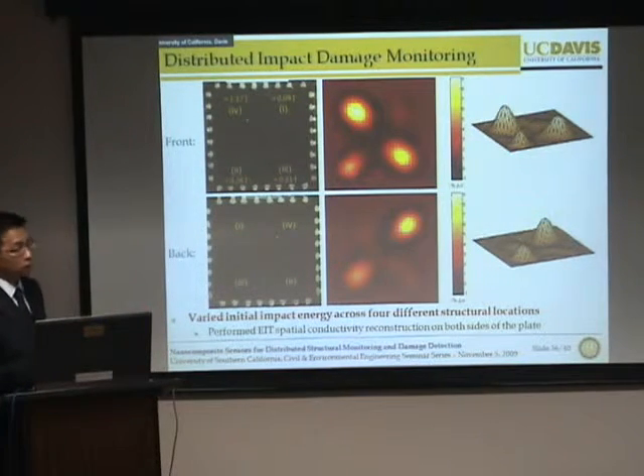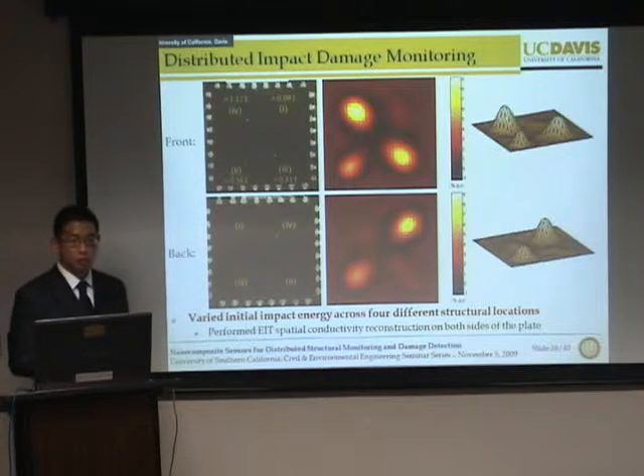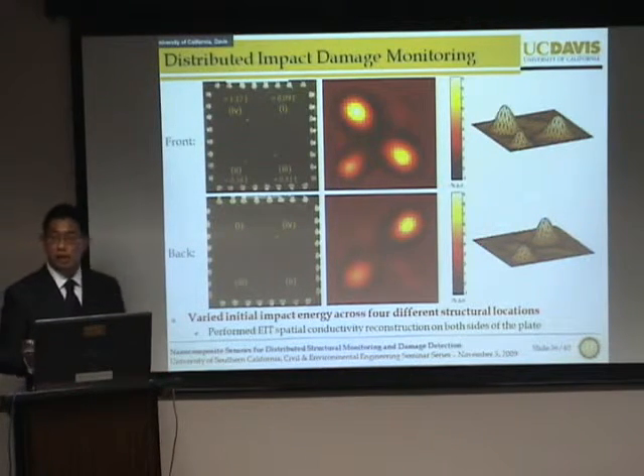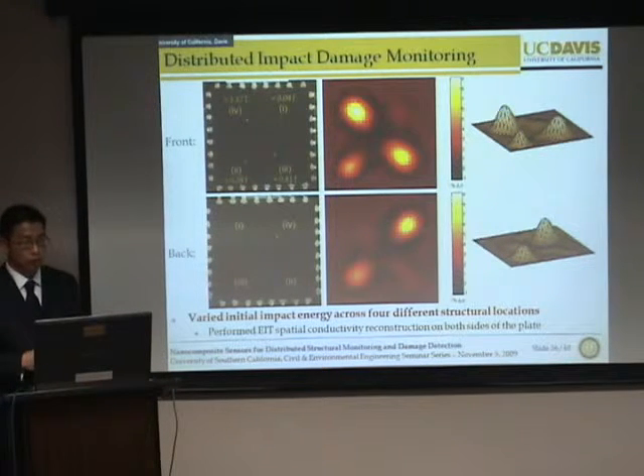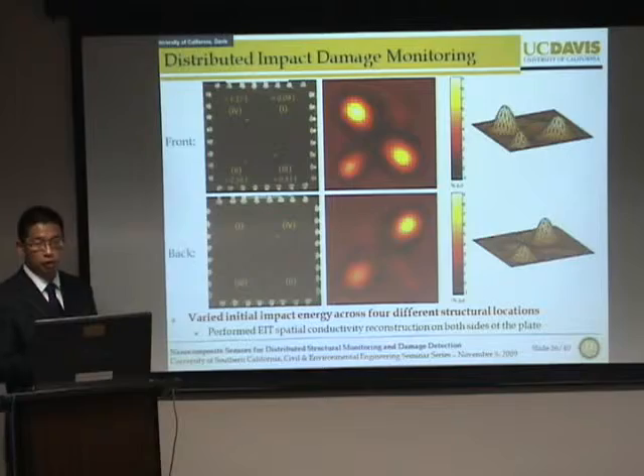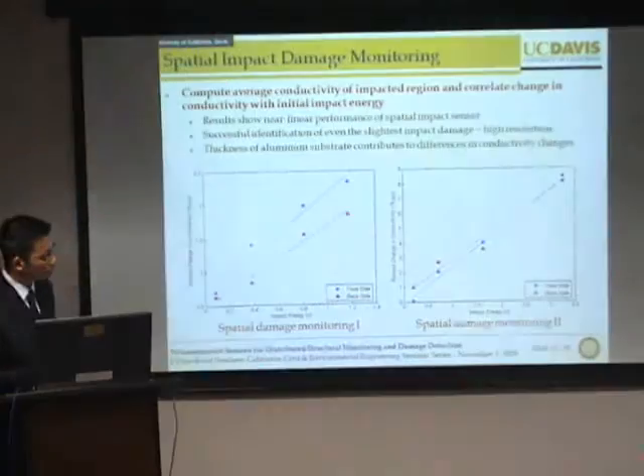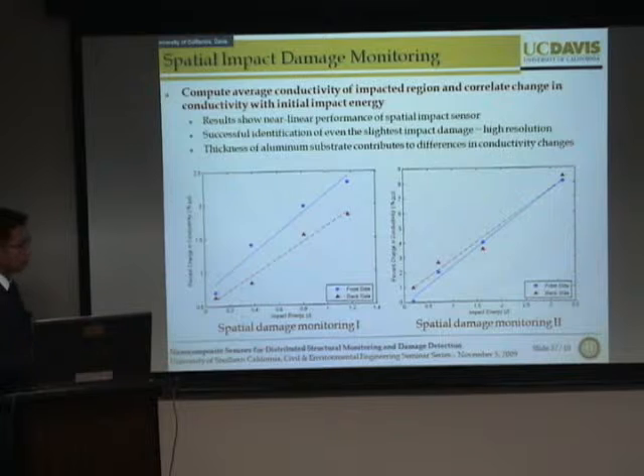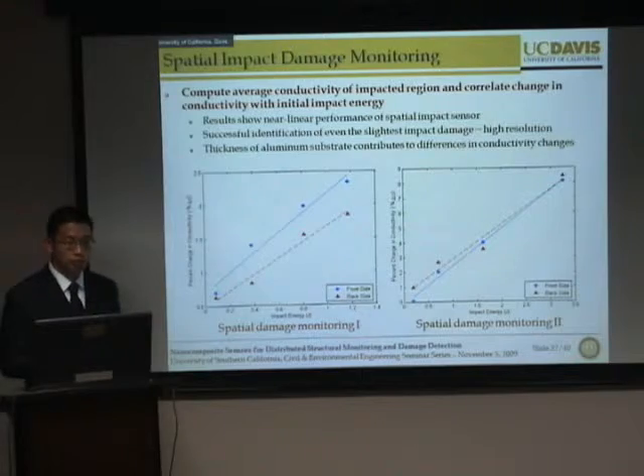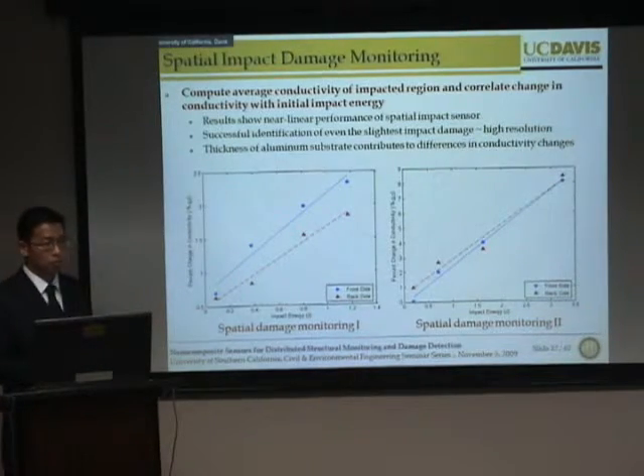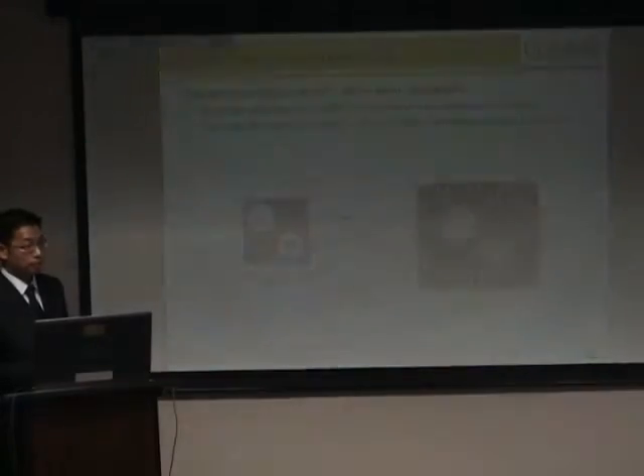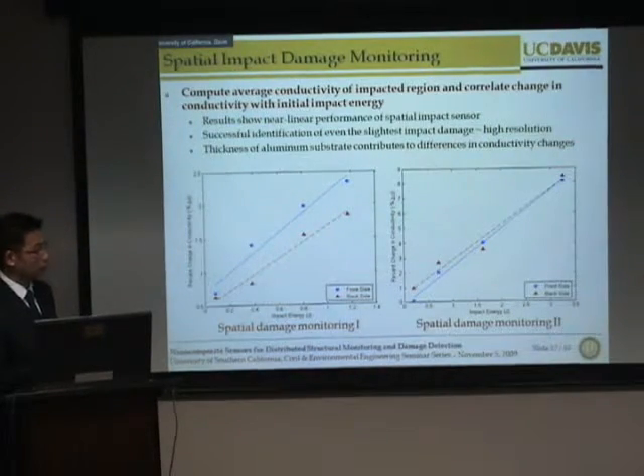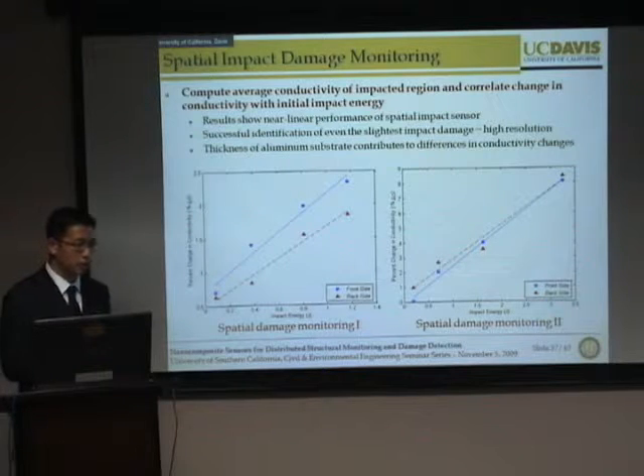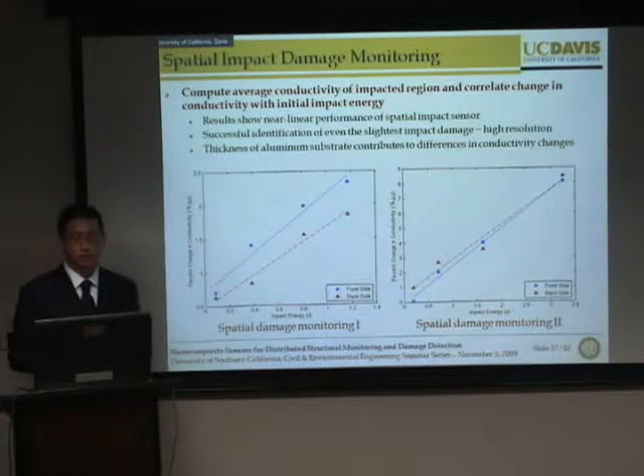So now with this technique, not only are we able to identify the magnitude of damage based on change in conductivity, we're also able to isolate where the location of damage has occurred. And you can see that we could plot it in 3D for easy visualization of damage. And we can do some data analysis to look at how the percent change in conductivity varies with impact energy. And we see that we do see some linear behavior. This is damage in the film itself, right? Or in the plate itself? In the plate? So there, we purposely try to inflict some permanent deformation on the plate.